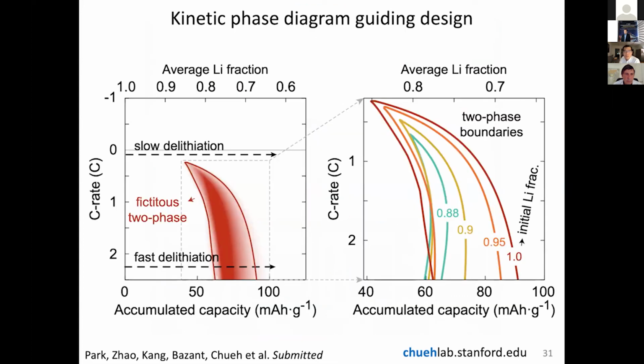So let me finish up here by showing the phase diagram. We now can construct a phase diagram to tell you where this would happen. It only happens when the reaction is getting faster with the extended reaction, but it doesn't happen in reverse. So for this particular battery material, it only happens on charging, but it doesn't happen on discharging. And the effect increases with the reaction rate. And this has nothing to do with diffusion.